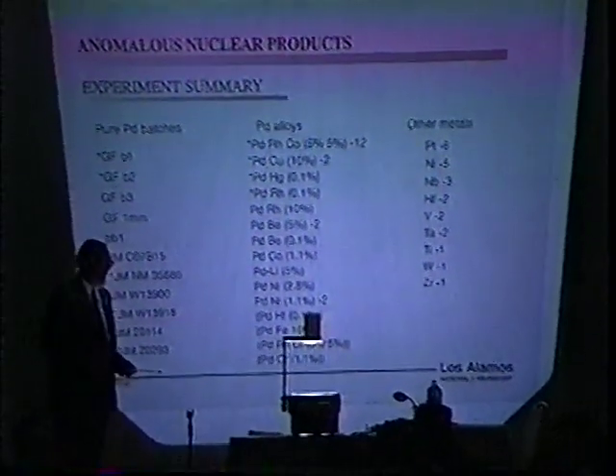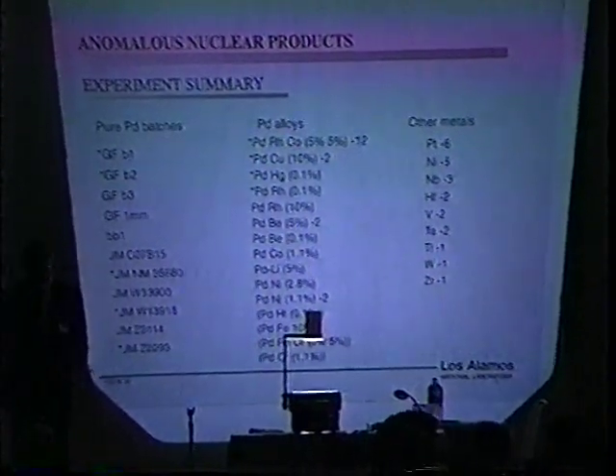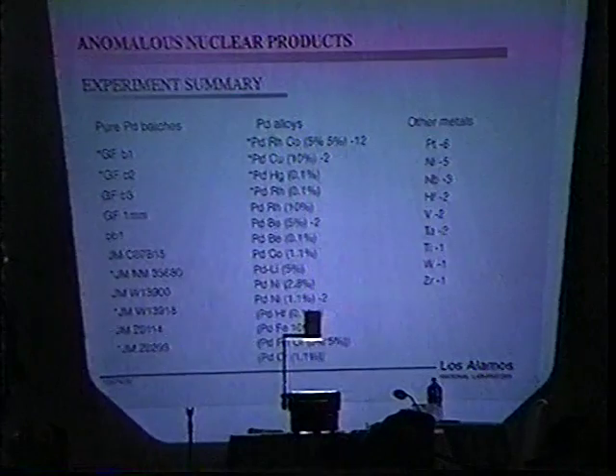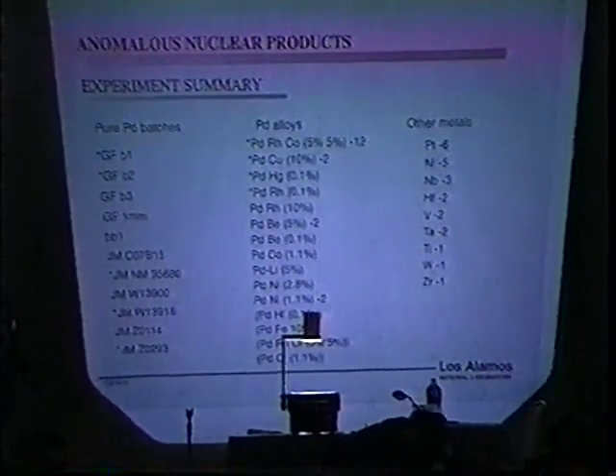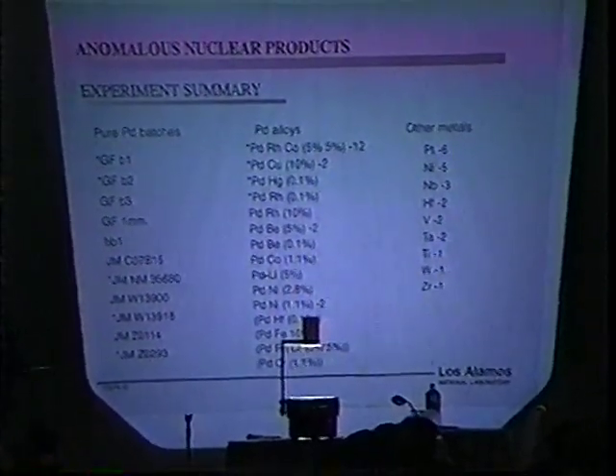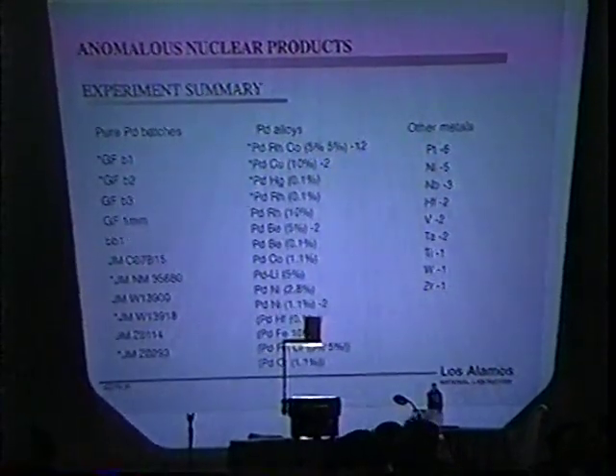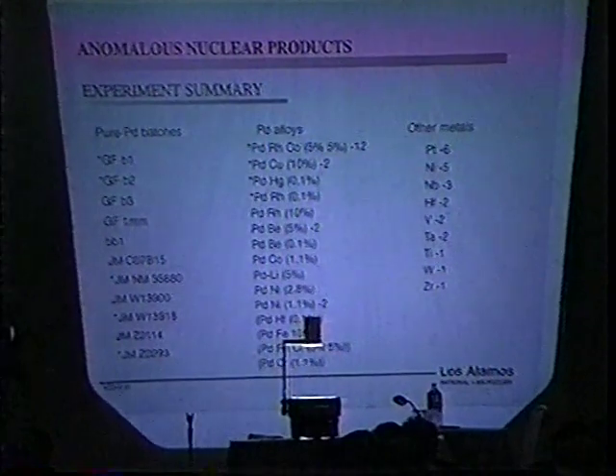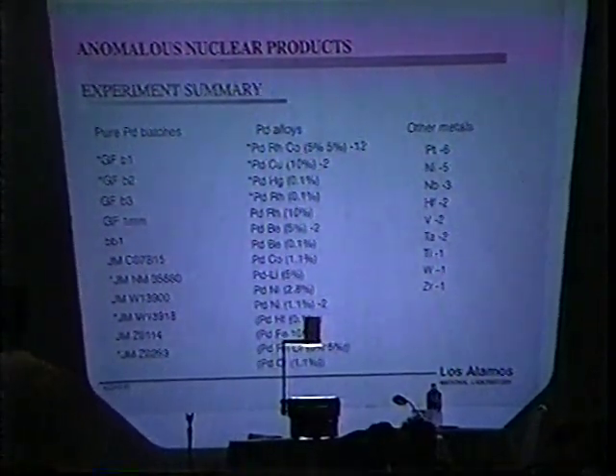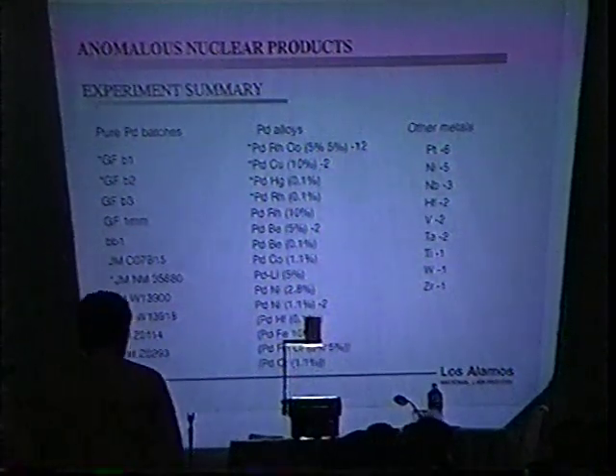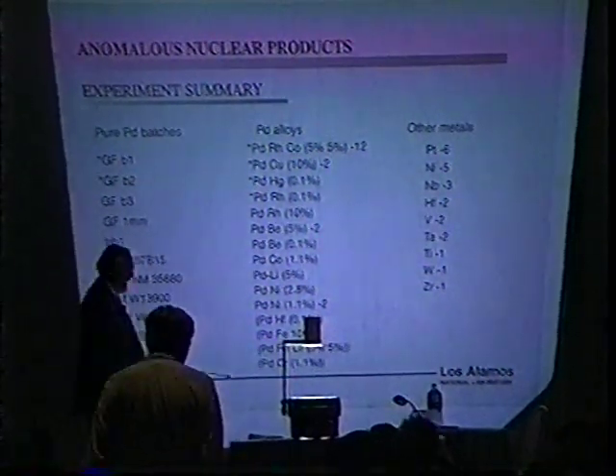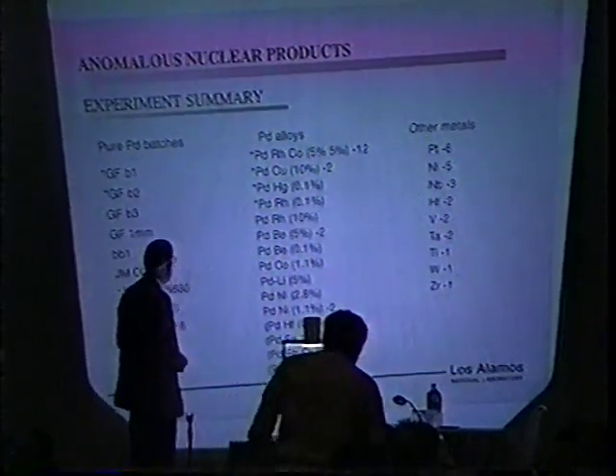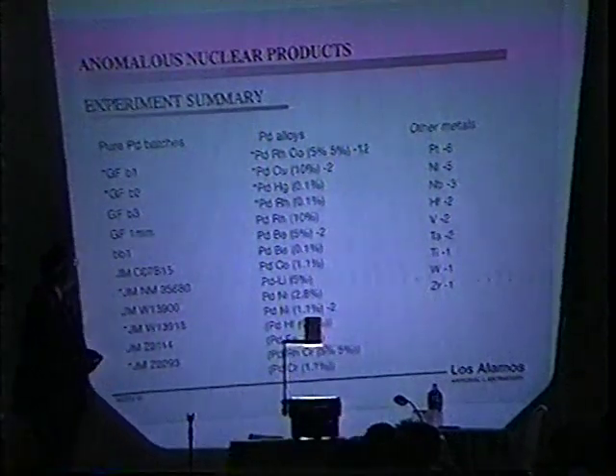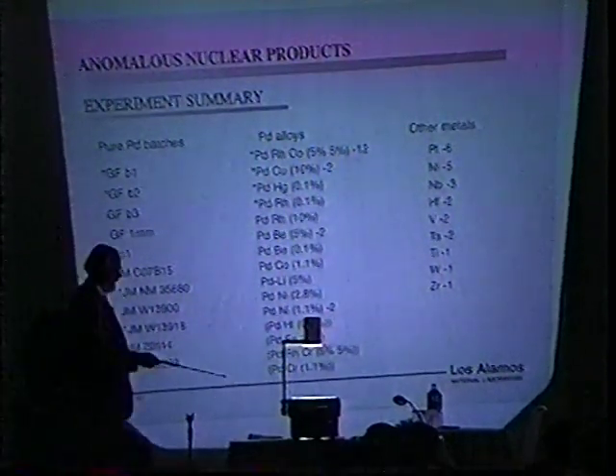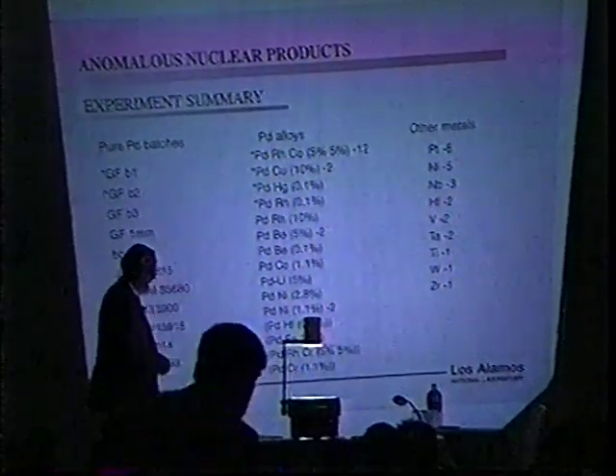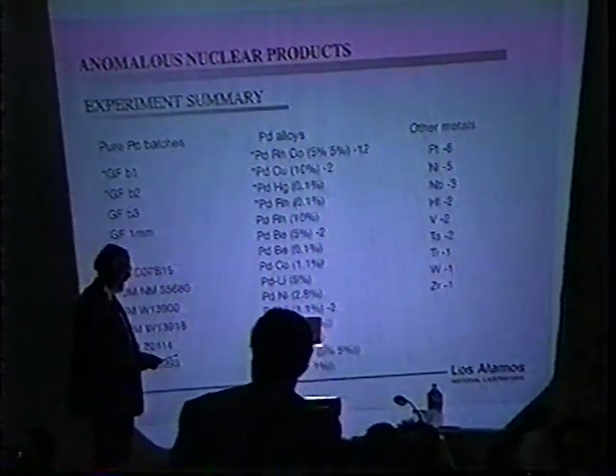But it was recognized that certain impurities in the palladium wire very likely play a role. But there are so many impurities, and at such low levels, it's very difficult to sort it out. So Tom started having alloys made up of various kinds in a brute force attempt to discover what effect these alloys might have and find out which ones are the source of the tritium. And the alloys that he studied are listed here. Some of these have been looked at, some of them have not. A number of them listed with the asterisk have in fact given excess tritium, but not to the level of the pure material.